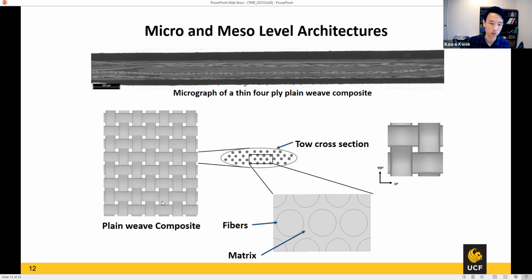But then you go to the next level architecture, the mesoscale architecture, where you see this woven layer. And also if you use more than a ply, then you get even more variation, because each ply, the plain weave pattern, they don't have to match up. So sometimes you have gaps between different layers, there are mismatches between those. In thin ply composites, these things matter a lot more than in traditional composites. So we see a lot more variability, from composite to composite in thin ply.